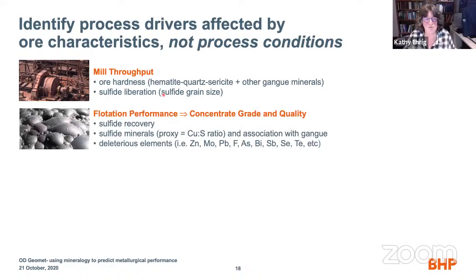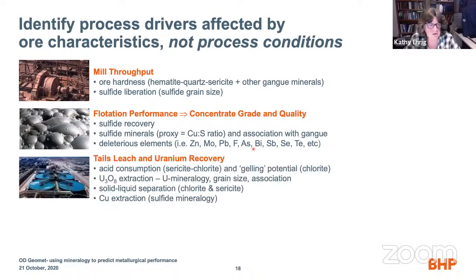Then you go to flotation performance, and flotation is all about making a copper concentrate, a sulfide concentrate. So that means understanding what the sulfide recovery is going to be, what the sulfide minerals are, and what little bit of gangue minerals end up in your concentrate, and all the deleterious elements that are either going to be harmful or potentially extra beneficial in the smelter, but also what are the ones that are going to impact on your cathode final products. In tailings leach, we actually have to worry about acid consumption. That's controlled by sericite and chlorite, and a thing called gelling, which is controlled by the amount of chlorite in the ore.